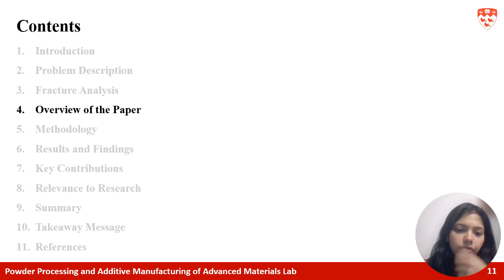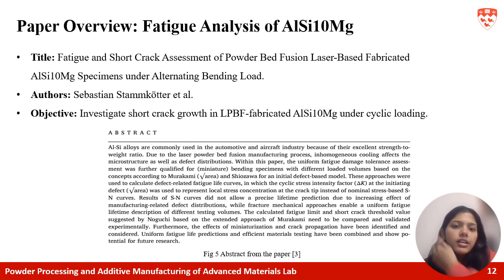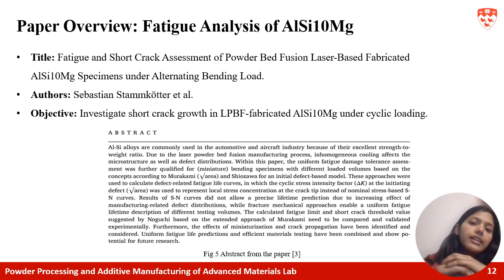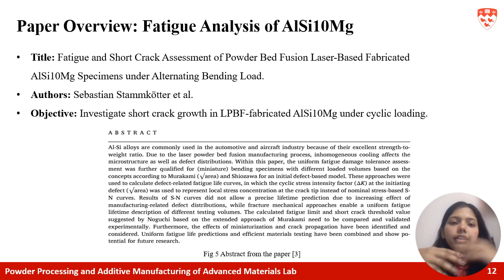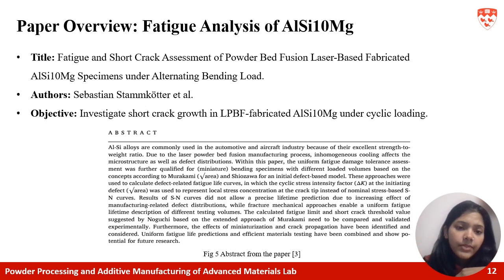So let's have an overview of the paper. Let me introduce the key study we'll focus on. So in this paper, the author investigated fatigue and short crack behavior in aluminum silicon 10 specimens produced by laser powder bed fusion. They focused on alternating bending loads to mimic real-world stresses. And the key takeaway here, they demonstrated how microstructural defects such as pores and inclusions significantly reduce fatigue life. The study is particularly relevant to my work because it connects material properties with performance, offering insights into optimizing additive manufacturing processes.